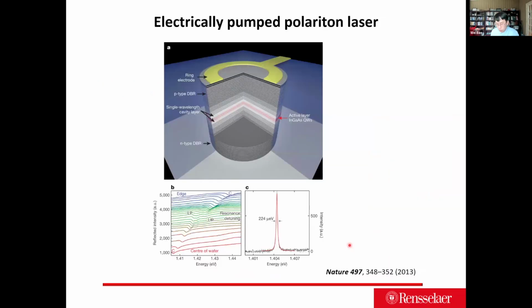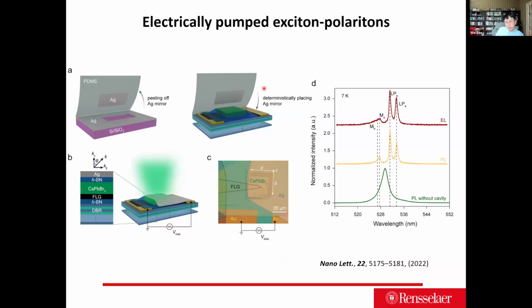Besides those, we also try to use perovskite to see whether we can achieve electrically pumped polariton lasing, which has been done in a Nature paper by Professor Sven Höfling's group. Just to give a short overview: we use silver and graphene, and essentially make a structure with a DBR, hexagonal boron nitride, graphene, and the cesium lead bromide, and then graphene, hexagonal boron nitride, and the silver, through a transfer process, and we use a capacitance structure. So essentially, at a certain time we inject one carrier through the graphene layer first, and inject the other carrier at another time.